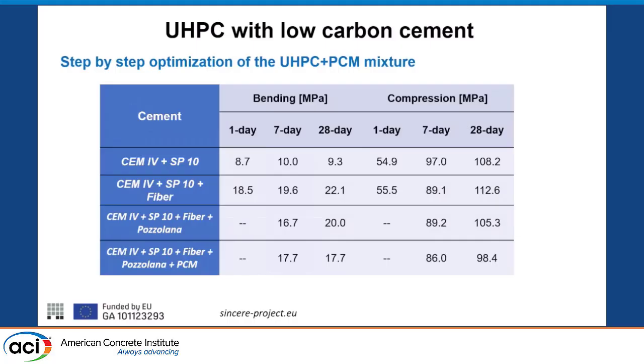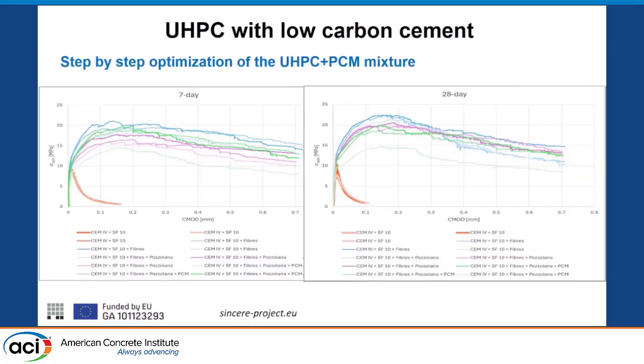And we were able to obtain a bending performance, which with the fibers you greatly increase, and this was a good performance also in terms of compressive strength. We obtained what we were looking for.